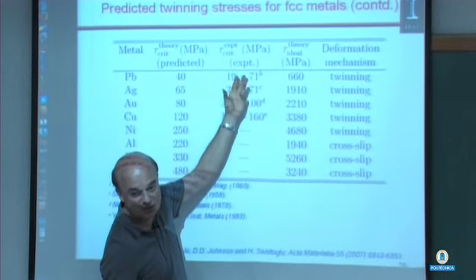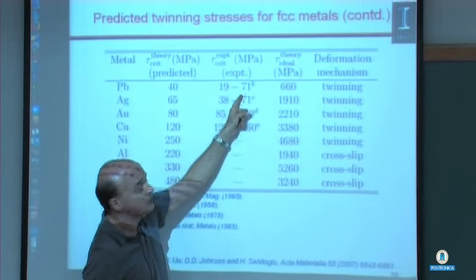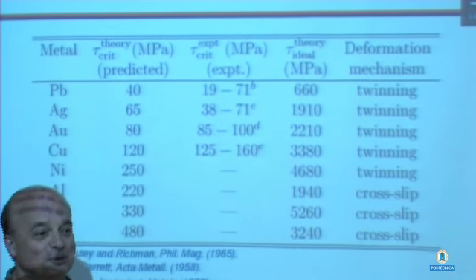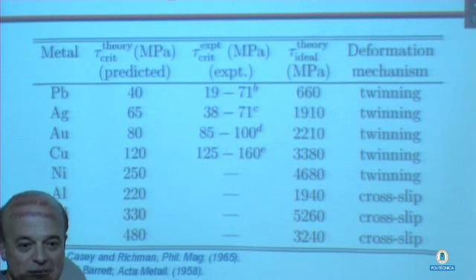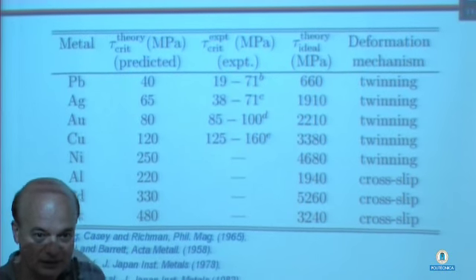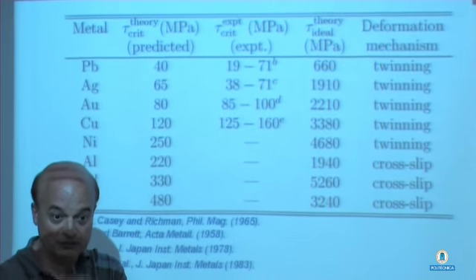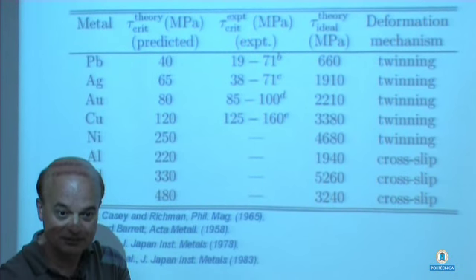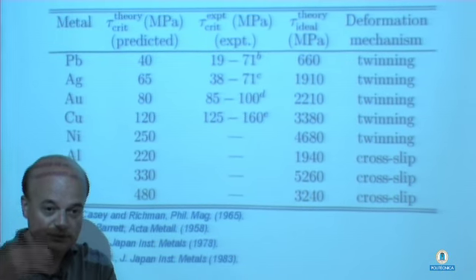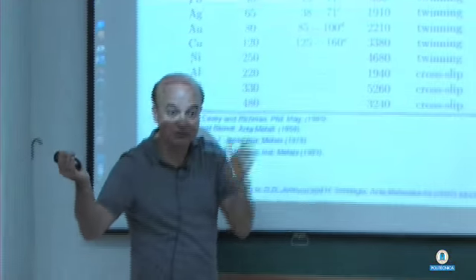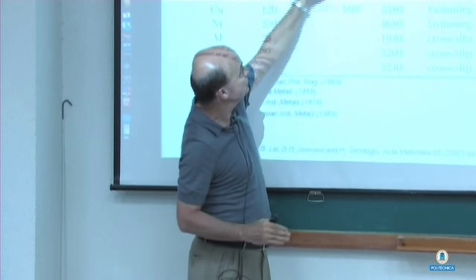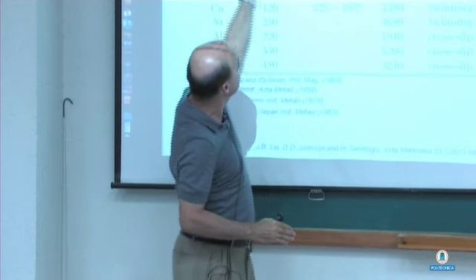The summary of the results: the critical stress experimental values in the literature have quite a bit of range. That's why you might need digital image correlation to pin this down, because somebody uses one technique, the other one uses another technique. They might report very different values of twinning stress. If they used, I don't know, position measurement or something like that instead of very fine resolution, they might get quite different values. But nevertheless, our predictions are right there.